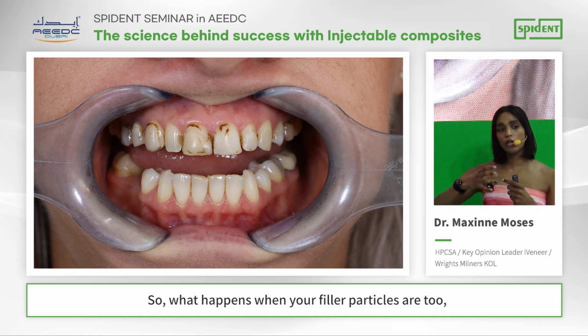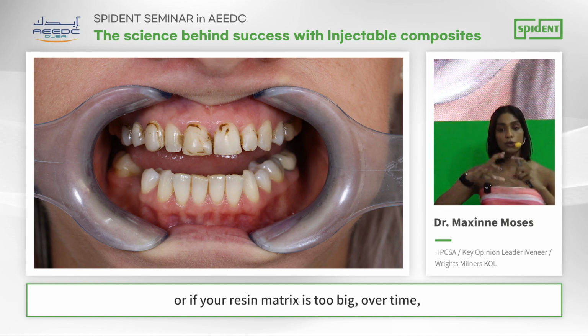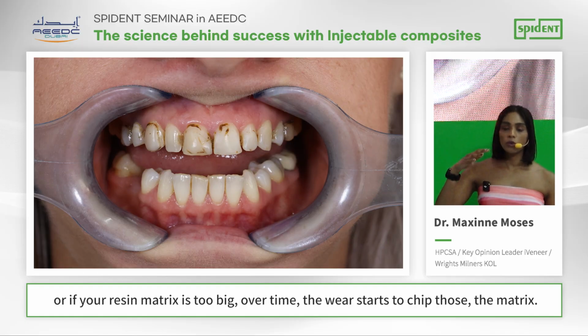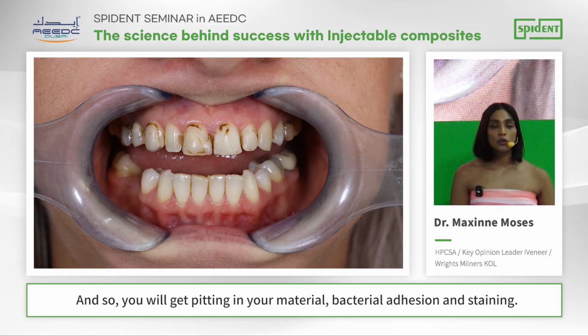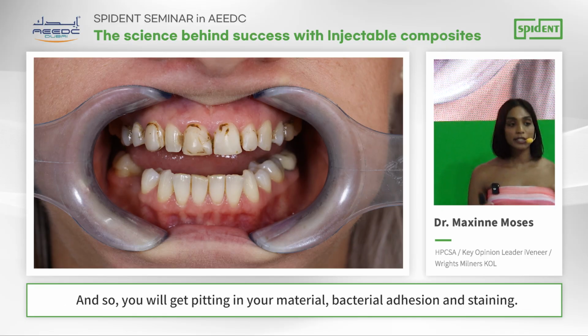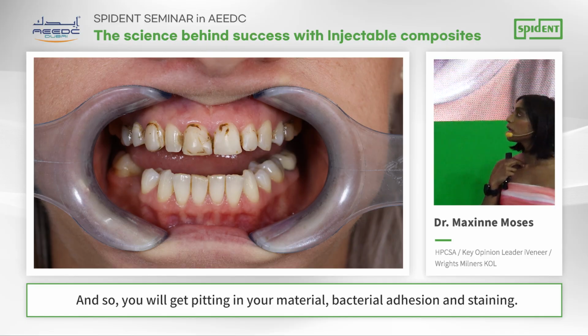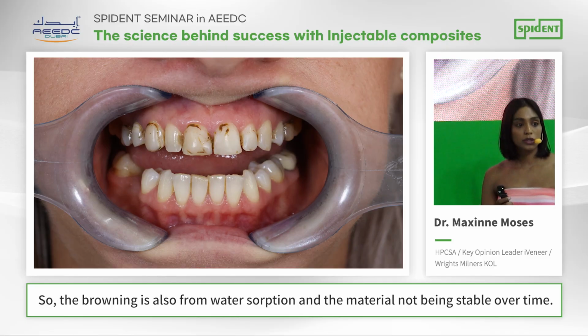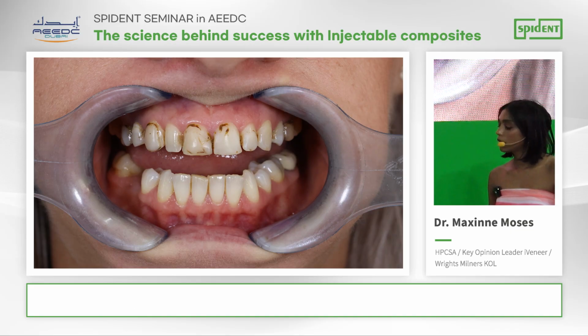So what happens when the filler particles in your resin matrix are too big, over time the wear starts to chip the matrix. And so you will get pitting in your material, bacterial adhesion, and staining. So the browning is also from water sorption and the material not being stable over time.